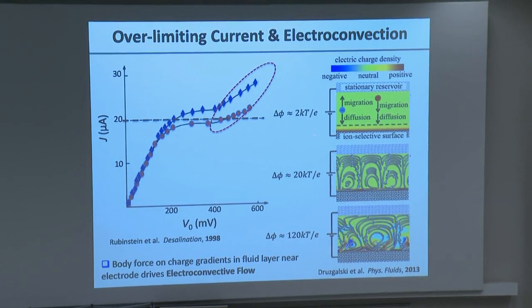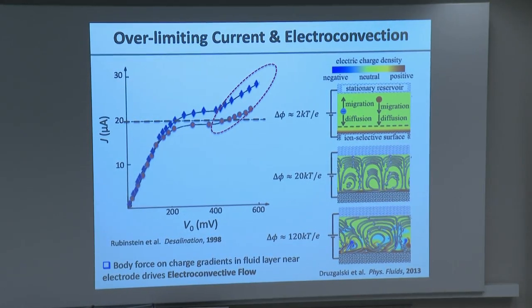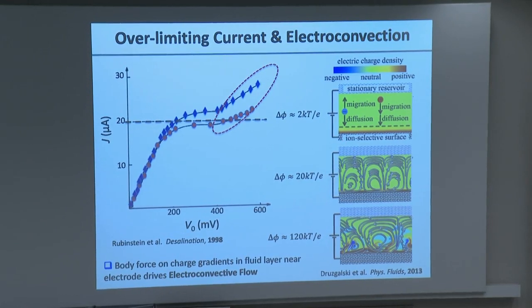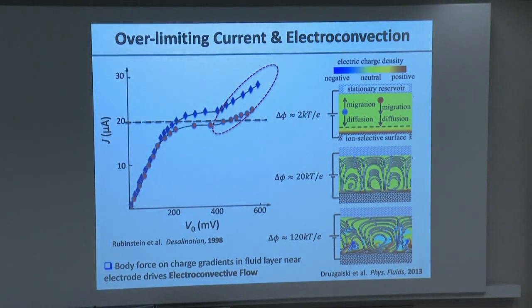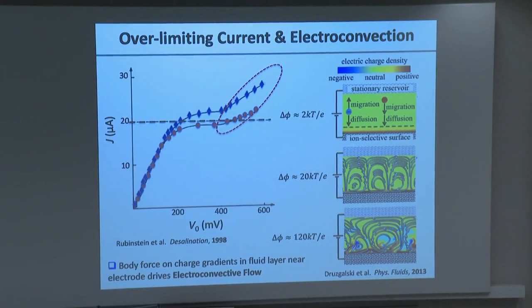The ions in the electrolyte are homogeneously distributed, more or less, in the bulk, except for a very small layer, the so-called quiescent electric double layer, or the Debye-Huckel double layer, as some of you may know it, that's affiliated to the surface that has a slight increase in positive charges because the surface is slightly negative in charge. When you drive the system at potentials above the limiting current, the prediction is that suddenly you start to create these rolls, these turbulent rolls. If you drive it even faster, what they discovered is that these rolls become chaotic and time dependent.